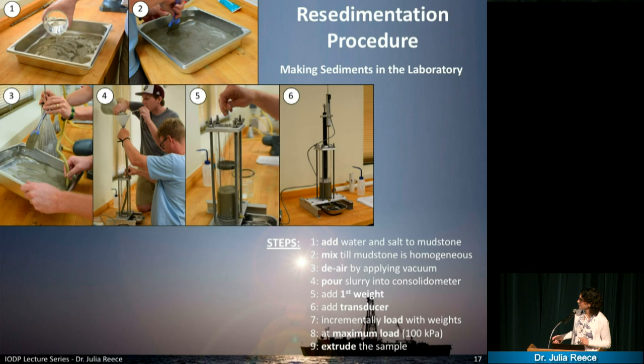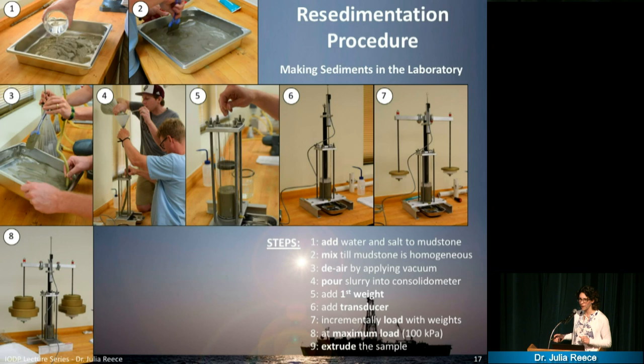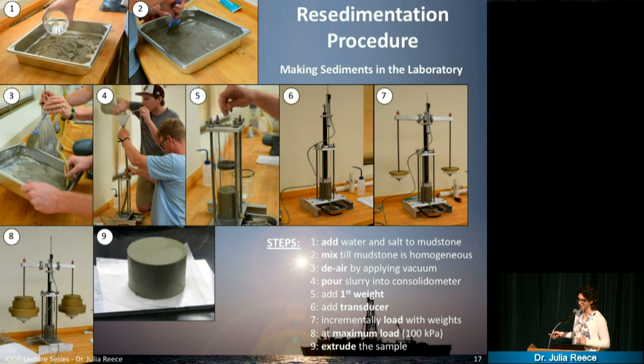And then this is at the maximum stress, which is a 20, 10, and 2 kilogram weight on each side. And that will take you to 100 kilopascal, which might not tell you much, but it would be the equivalent of 10 meters of burial. So not much at all, but we went from something very soupy to something that you can actually touch and squish, and you can then do further experiments with these and see how the porosity has really changed as we added more stress onto these samples.